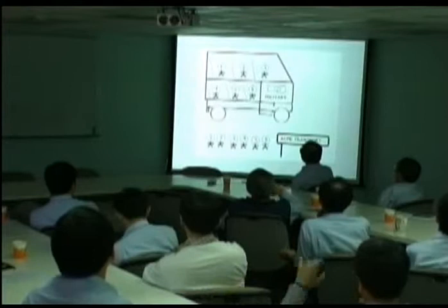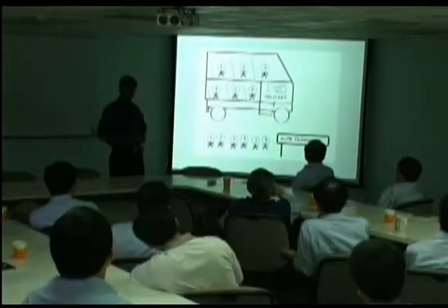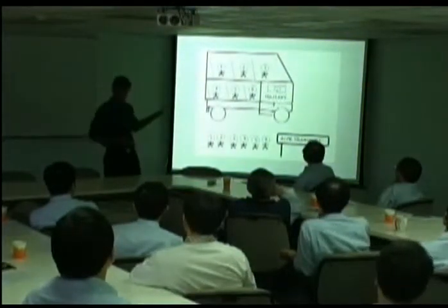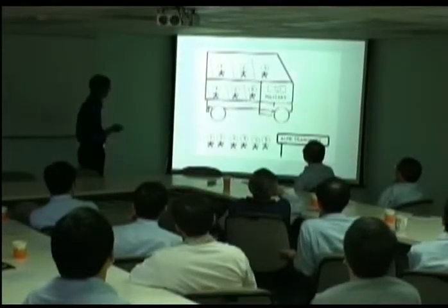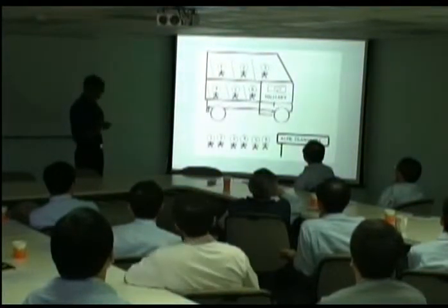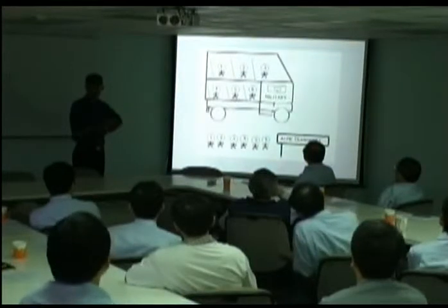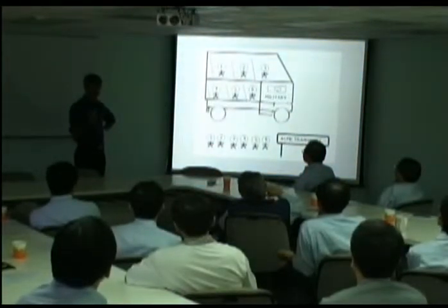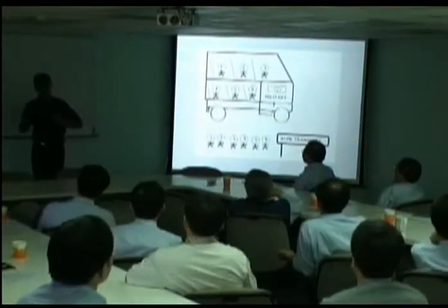Now, there's another way of looking at mechanisms of transformation. Let's imagine that we have a queue of soldiers here, and these are their names, 1, 2, 3, 4, 5, 6, and their military transport arrives, and they're ordered to board the transport, and they board it in a disciplined way. So we know that number one is still next to number two as in the queue. So we have an atomic correspondence between positions inside the bus and positions in the queue. A coordinated movement of atoms. So that's martensitic transformation or the growth of bainite. Now notice that if soldiers one and two don't like each other, they have no choice. So there would be a lot of strain energy involved in such a transformation. So this is what we call a military transformation, martensite or bainite.